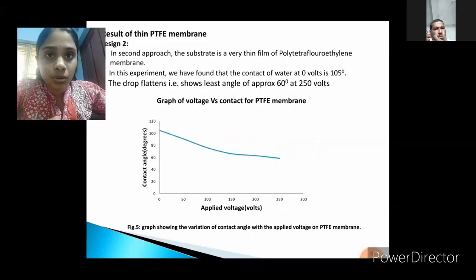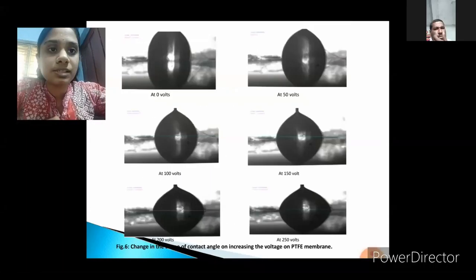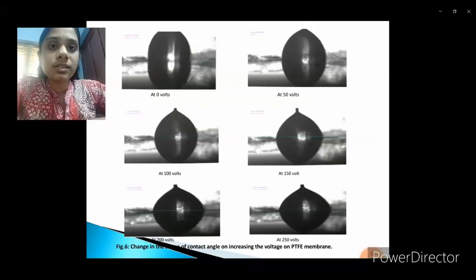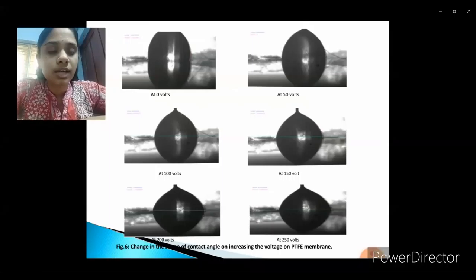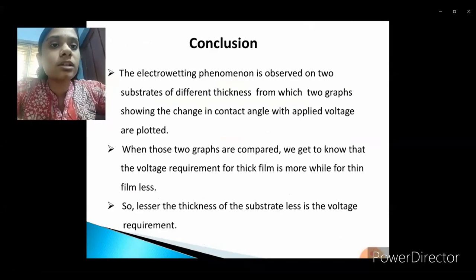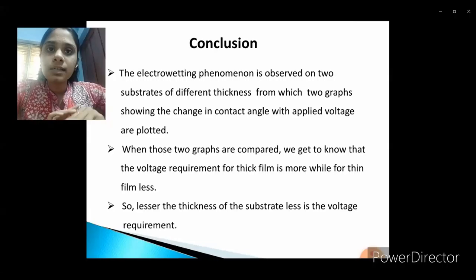So, conclusion. We have taken two substrates with different thickness and from that we have plotted two graphs. From those graphs, we have concluded that the voltage requirement for the thin film, meaning the substrate having less thickness, is less as compared to the Teflon tape. So we can conclude that the lesser the thickness of the substrate, the less the voltage required.